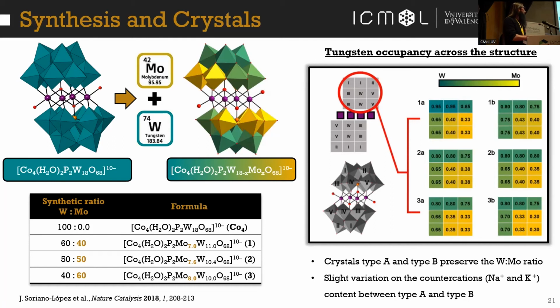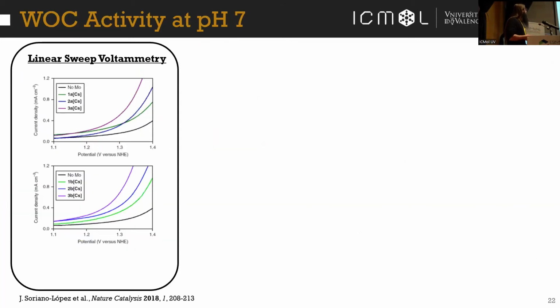And when we move through the structure of the polyoxometalate to these positions, we start finding more molybdenum. So basically all crystals type A and B preserve the tungsten to molybdenum ratio. So from each synthesis, we have 2 different crystals that present the same tungsten to molybdenum ratio, and the only difference is a slight variation of the countercations because we use sodium and potassium as countercations. So we took these 6 crystals, we precipitated the cesium salt of the crystals, and we ran more water oxidation tests. This time they were under neutral conditions.